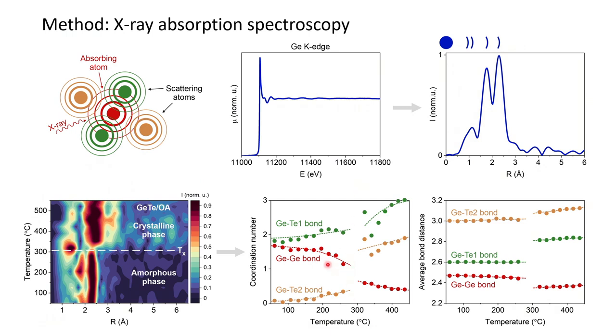So what do we see? We see a discontinuity, which points us to the fact that there is crystallization happening at about 300 degrees C for the sample. So of course, while crystallizing, the atomic structure rearranges, and the bonds that we have change their lengths quite abruptly in this case, and also the structure is getting linked differently between crystalline and amorphous.